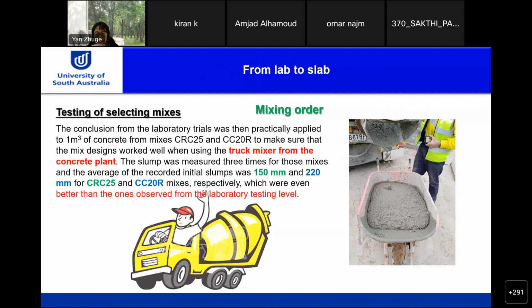And then the optimal mix design from lab to slab was practically applied to 1 meter cubed of concrete using a large concrete mix. Okay? So the conclusion from the laboratory trials was then practically applied. We used 1 meter cubed of concrete from a mix of CRC25 and CC20R concrete to make sure that the mix design worked well when using a truck mixer.